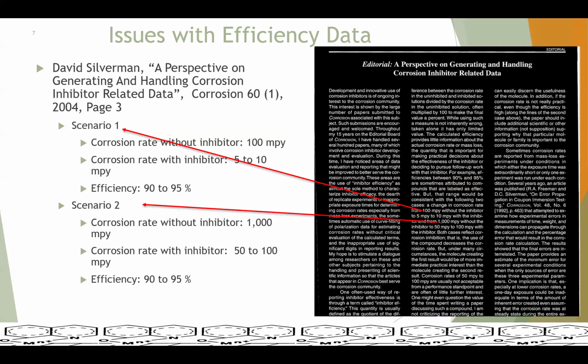In scenario 2, the laboratory reported 1000 mpy of corrosion rate. That is 1 inch per year of corrosion rate in the absence of corrosion inhibitor. And in the presence of corrosion inhibitor, it reduces to 50 to 100 mpy. Again, they report the efficiency as 90 to 95%.